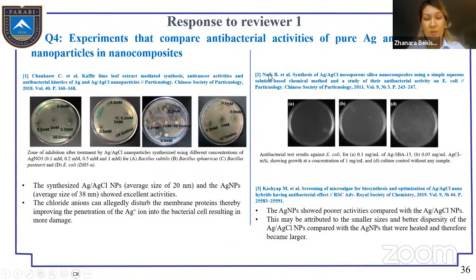And the experiments comparing pure silver and silver chloride nanoparticles. In this work, silver chloride on SBA-15 and metallic silver nanoparticles were studied. The silver chloride shows more antibacterial efficiency at a lower concentration. We can see that the silver chloride nanoparticles, at this concentration and with an average hybrid particle size of 20 nanometers, show more excellent activity than the metallic silver nanoparticles.